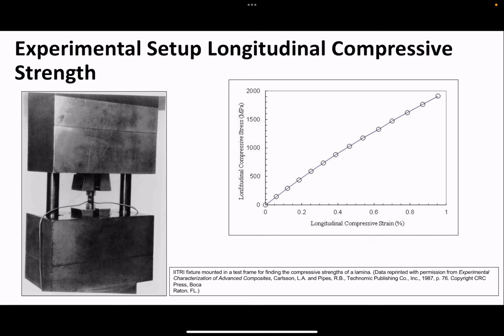You can get the slope, which is the Young's modulus in the compressive direction, which is E1C, for graphite epoxy as well. E1 compression is 199 gigapascals, which is pretty impressive, right? It's almost close to steel, very close to steel, equal to steel actually. And sigma 1C ultimate is a lesser value than your tensile strength, as well as the strain is also less than your tensile strain, 0.995%. While there, the strain was 1.56%, which means it could stretch a lot more than it can get compressed. Right? This is typical and expected, but the Young's modulus holds up pretty well.